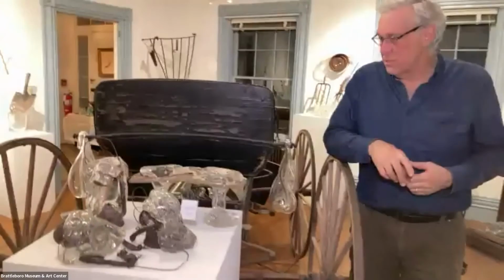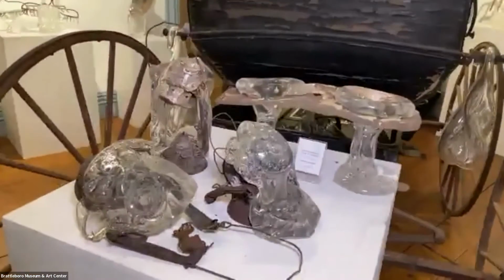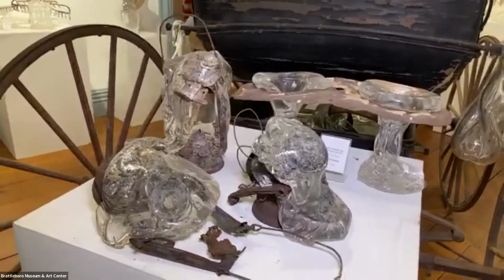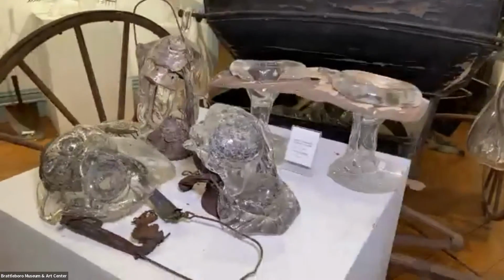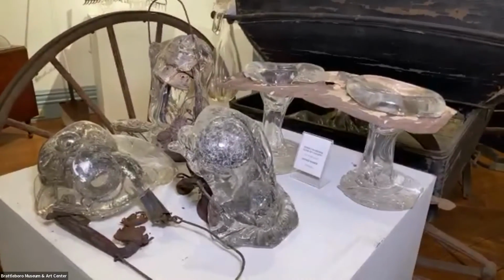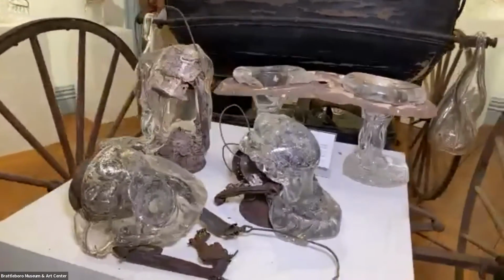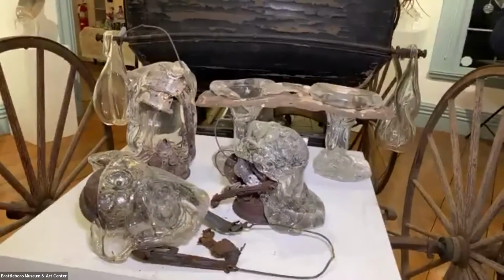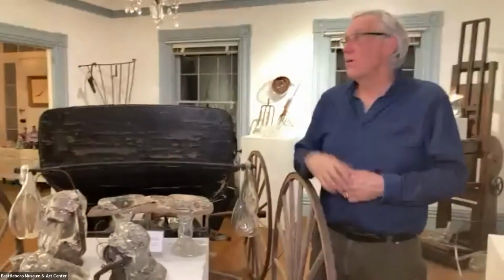I don't know what. So we had lanterns. These were old kerosene lanterns that were actually for our wedding that we had up there in 1995. And that was the first thing I worked on. I sort of started pouring glass and almost imagining that there was a glass jar above the lantern that melted and actually encased it. What was really amazing was that none of these cracked. And normally when you combine glass and metal together, the coefficient of expansion is different. And what happens is one will shrink more and the glass will shatter. So the first morning when I opened up the kiln and nothing had cracked, I was like, oh my God, this is amazing. So I started really playing.